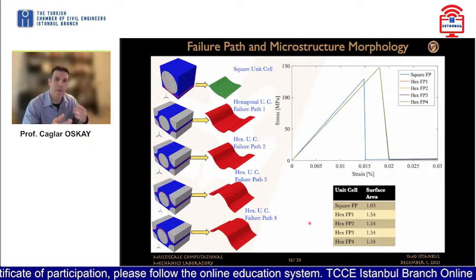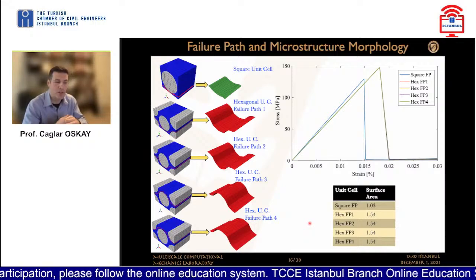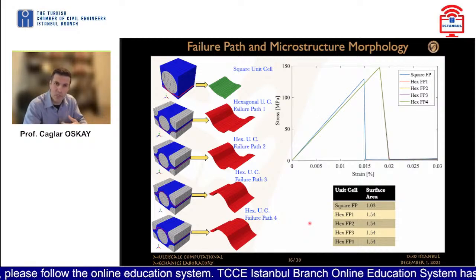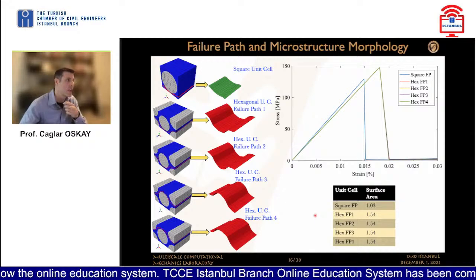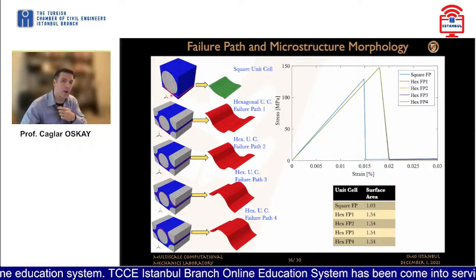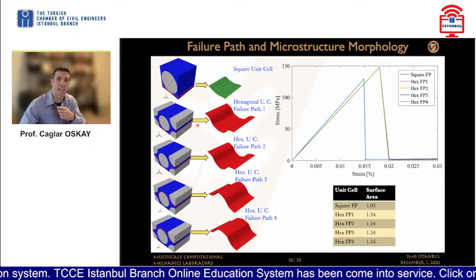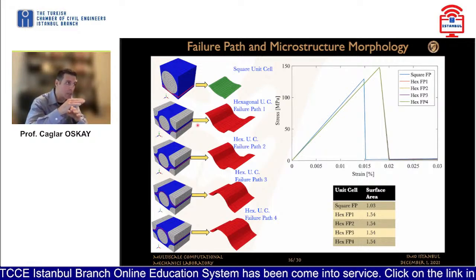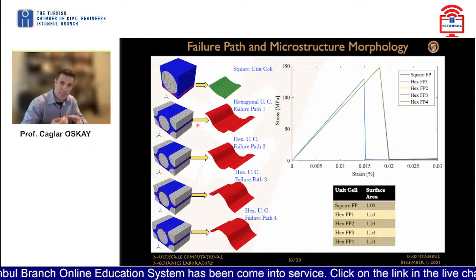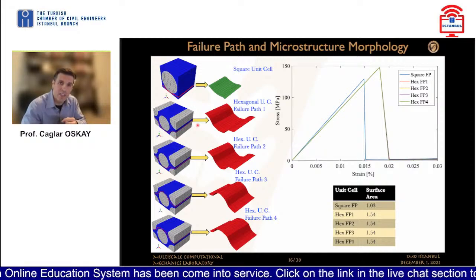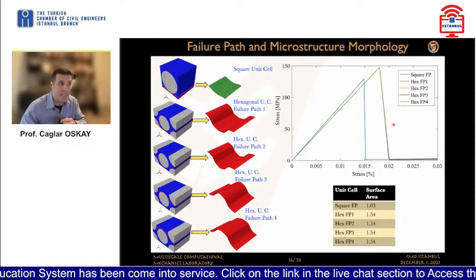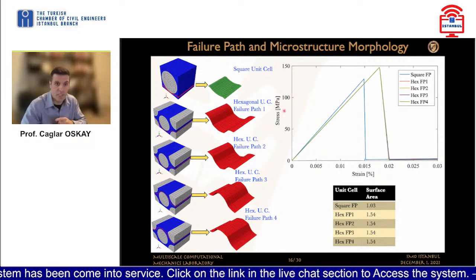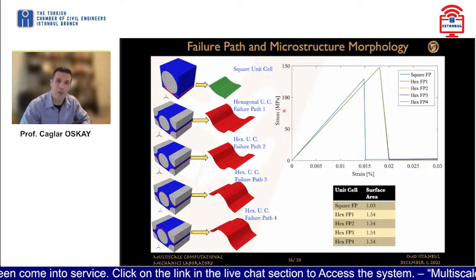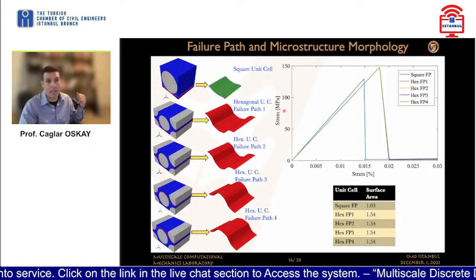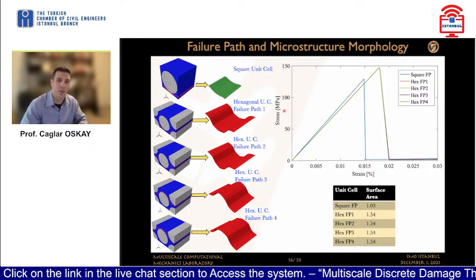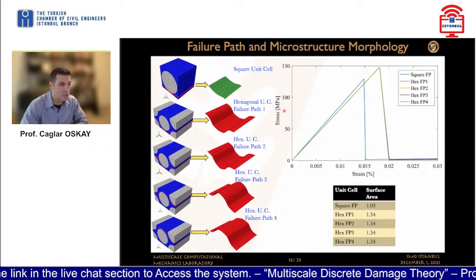One of the nice things about the MDDT approach is that we're now directly embedding the material microstructure. So the microstructural features and the geometry of the microstructure start to affect the overall response. Here, for instance, we're showing the differences between a square unit cell and a hexagonal unit cell, where in the hexagonal unit cell, the crack necessarily needs to be tortuous compared to a square unit cell, which could be very flat. That means that the amount of area that the crack needs to go through is larger. Therefore, it leads to a larger energy density as well as dissipated energy, as well as strength of the system. So that allows us to consider the effect of microstructure in the model. Connected back to what I was saying at the beginning is the ability to innovate material microstructures that will behave well depending on what kind of property you see at the structural scale.